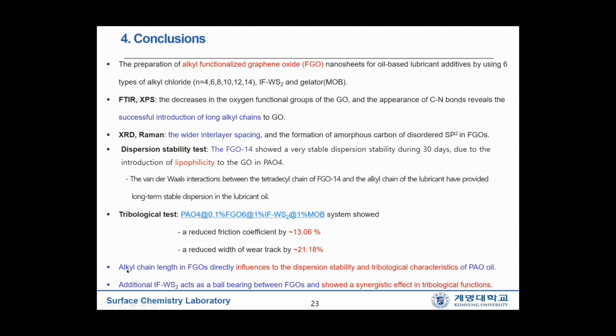Therefore, we observed that alkyl chain length in FGOs directly influences the dispersion stability and tribological characteristics of PAO oil. Finally, we observed that additional inorganic fullerene-like tungsten disulfide acts as a ball bearing between FGO sheets and shows a synergistic effect in tribological functions.